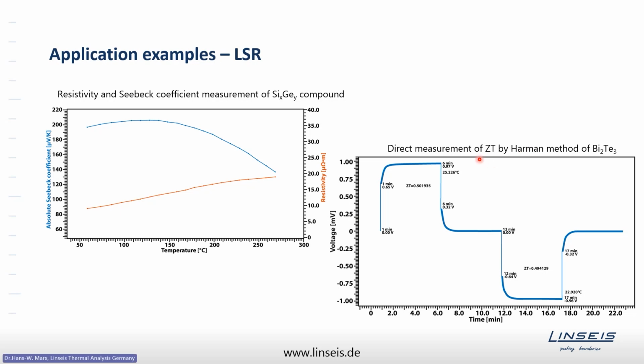In the beginning, we saw that the so-called Harman method, which is an option, an add-on for the LSR instrument, allows us to measure the figure of merit directly without going via electric conductivity, thermal conductivity, and the Seebeck coefficient. In this example, the measurement of the figure of merit of bismuth telluride is shown. So you see the measured voltage over time after switching on an electrical current.